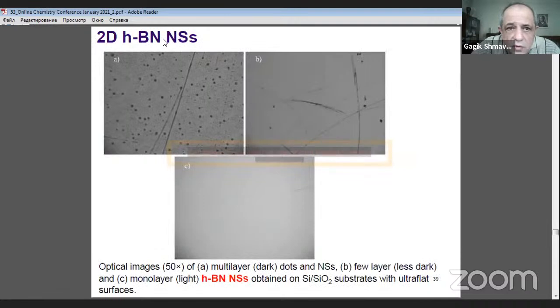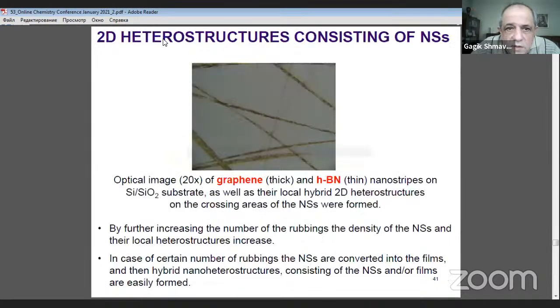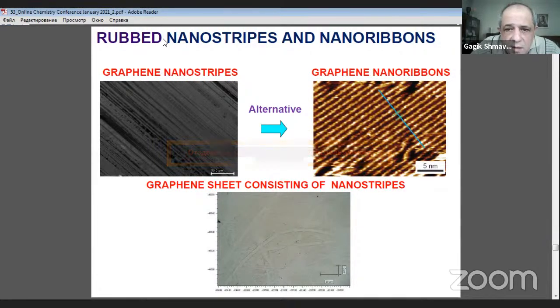Here we also carried out boron nitride powder rubbing, and you can see we get the same behavior. Here you can see Raman spectra of hexagonal boron nitride nanostripes, and the transition from bulk boron nitride powder to monolayer boron nitride nanostripes. Here you can see a 2D heterostructure consisting of nanostripes of graphene, the thick lines, and thin lines which illustrate hexagonal boron nitride. From this you can see that graphene nanostripes are very similar to graphene nanoribbons, and you can see the sheet of nanostripes in the image below.